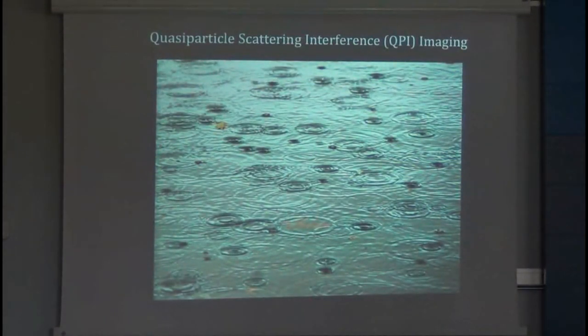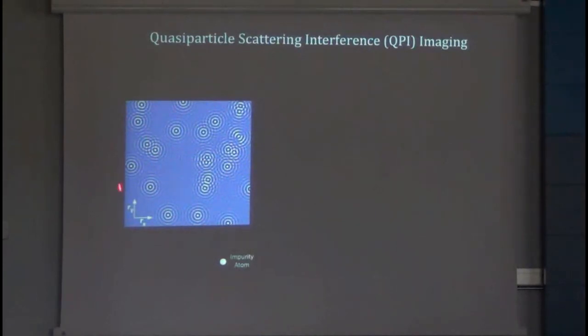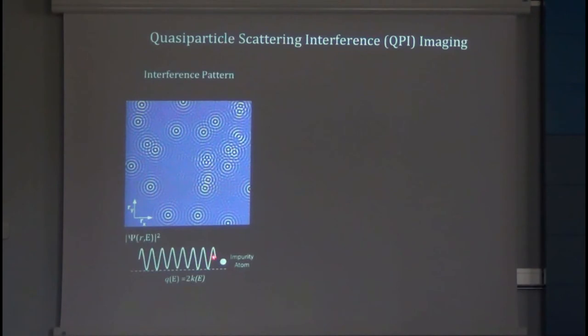First thing I want to tell you about is how to use this thing to measure the momentum space electronic structure. So imagine an impurity atom embedded in an electron fluid. An incoming quantum wave, a de Broglie wave with this wave function and this wave vector, hits the impurity atom and is reflected. If the scattering is in the correct phase, then you can add these two wave functions together. And when you add these two wave functions and square, you get something which has twice the spatial frequency, the Q vector of this modulation. It has half the wavelength or twice the Q vector. So this interference pattern at each impurity atom has a standing wave surrounding it, and that standing wave has a Q vector which is twice the K vector of the de Broglie wave that produced that interference pattern.